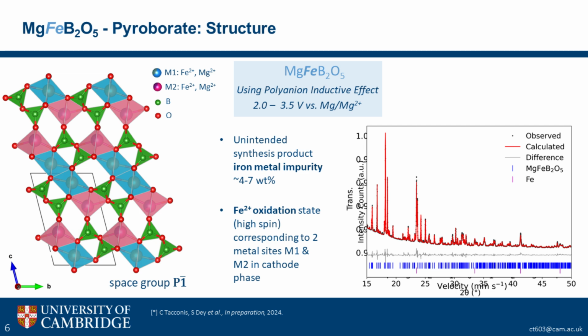So we did some Mossbauer. Don't worry if this isn't yet entirely clear to you. In a couple of slides, I'll go more in depth into Mossbauer spectroscopy and what that means. But I just wanted to show here close to the CIF, the crystal image, that we have 2 distinct iron 2+ sites, which correspond to the 2 metal sites that have slightly different chemical environments due to the disorder of the M2. So we're able to really look in depth at where the iron sits in the crystal structure. And we were again able to see in the Mossbauer with this sort of 4-peak yellow signal, the iron metal impurity.